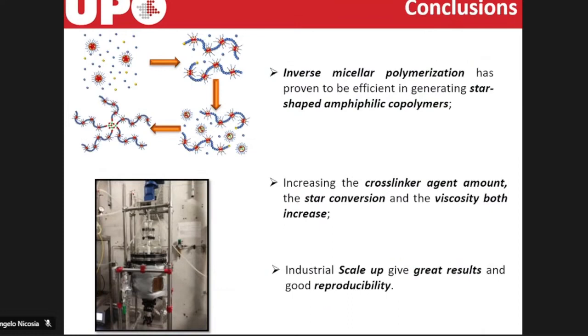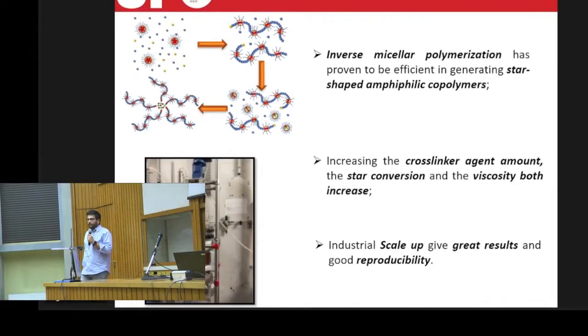So in conclusion, we can affirm that inverse micellar polymerization has proven to be efficient for generating star-shaped amphiphilic copolymers. We observe that by increasing the cross-linking agent amount, the star conversion and the viscosity increase. And the scale-up of this reaction gives great results and great reproducibility. So thank you for your attention.